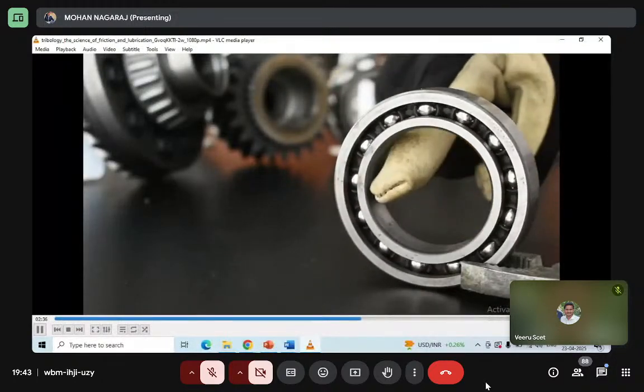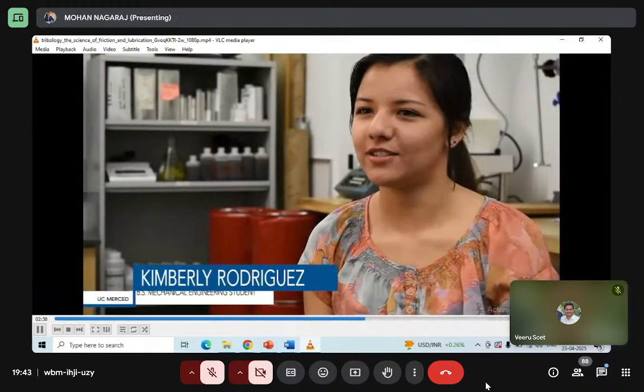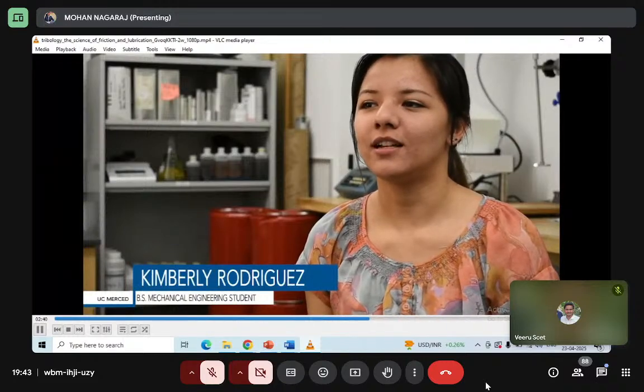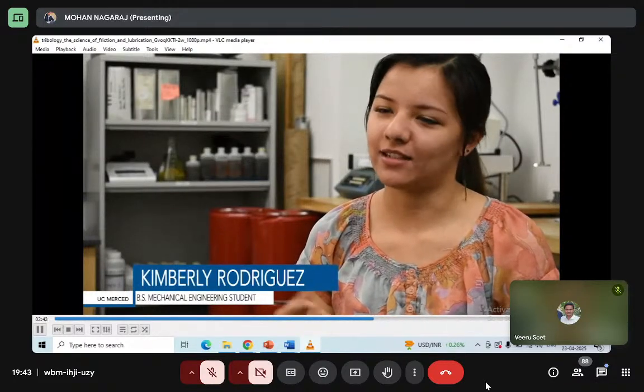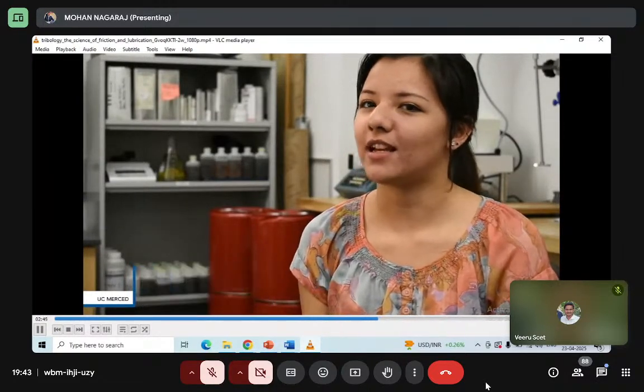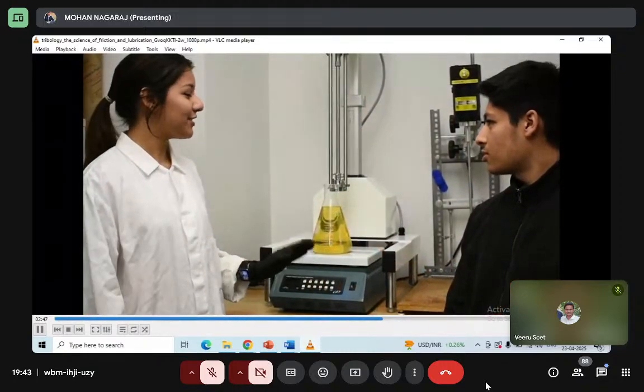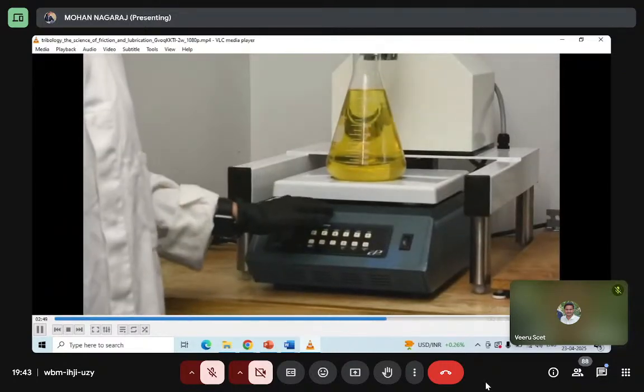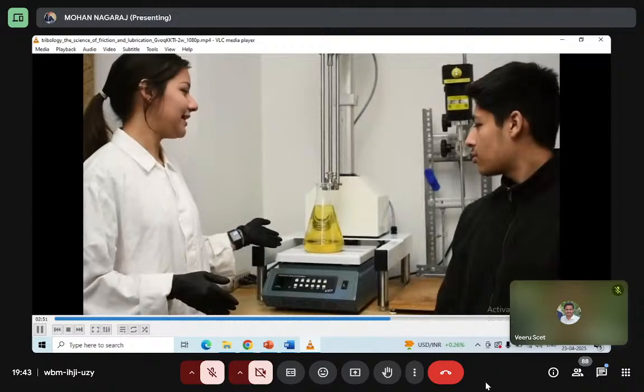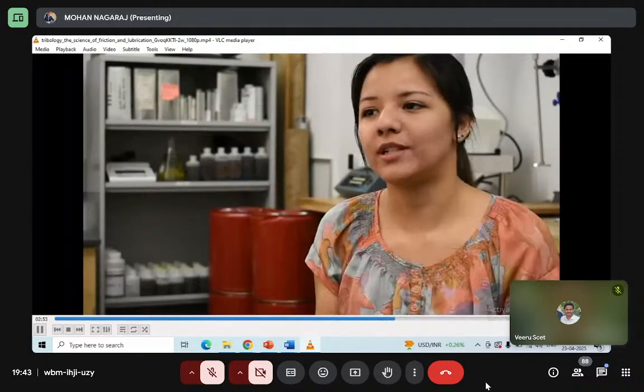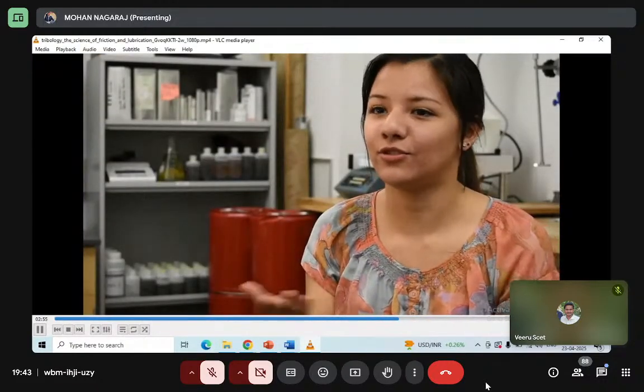So each sample that we create here has different additive combinations, and these are meant to keep the oils stable throughout varying temperatures and in the long run. What we also do is make sure that these oils don't produce foam. Once it starts developing foam, then you have bubbles, which pretty much exclude the oil, and you have the materials rubbing against one another, which produces the wear, and you lose energy from friction.